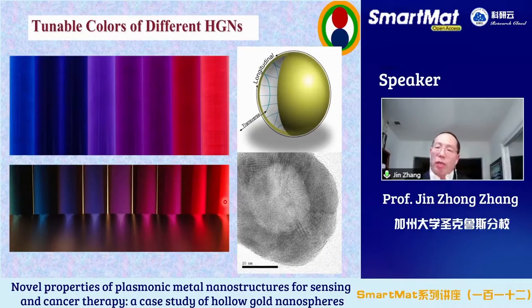This is the picture you saw on my first slide. All these are just as-made gold nanoparticles, hollow gold nanoparticles. We did a lot of images, hundreds of them. Here's one real image, and here's a cartoon, okay? It's a 3D structure projected onto a 2D plane, therefore it looks like a donut, but actually, it's spherical, okay? And each one is a sample. This is just a photograph of that. You can see any color you want, right? Blue, actually one of the samples is blue like ink, some are purple.